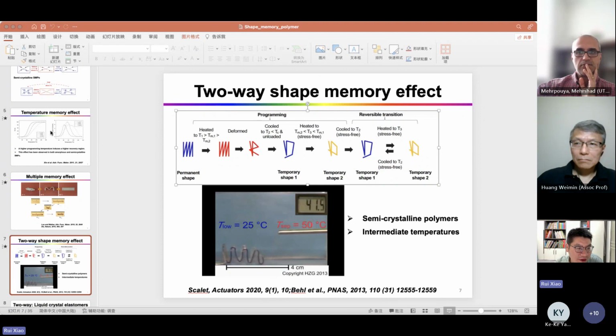Basically, at low temperature, the mesogens have alignment, but at high temperature, the mesogens are in random directions. So if you heat and cool, the two shapes can change with each other. Compared with SMPs, the reversible strain is actually very large—we can easily achieve a strain of more than 60%, even 100%. If we apply stress, the reversible strain is even larger.